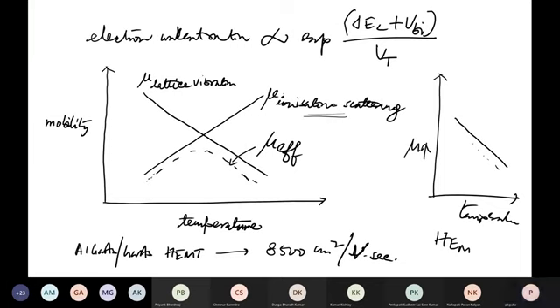Okay, which is almost 8 times that of the ordinary bulk silicon electron mobility. Okay, so this is at room temperature. If we reduce the temperature, it will be much higher. Okay, so this is in the HEMT. In case of bulk MOSFET, the electron mobility is even lower. It's not even 1300. It's like maybe 500-600. Okay, so you see there is a huge improvement we can achieve in case of aluminum gallium arsenide based HEMT structure. Now how this HEMT structure looks like,